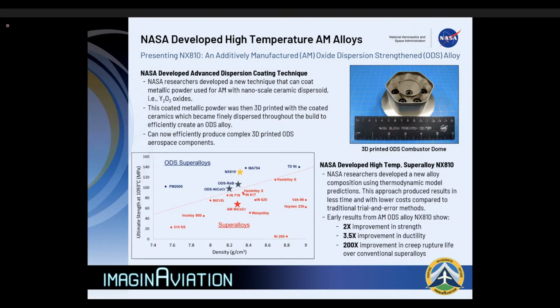And lastly, if we look at its creep rupture life, so basically the life of the component under a static stress at this high temperature, right here on the graph we're seeing a 200x improvement compared to nickel cobalt chrome and other conventional superalloys. But the fact is that those tests were actually still running when we made this graph, and we're now getting to the point where we're seeing 1000x improvement in its creep rupture life compared to nickel cobalt chrome. So you can imagine we're in temperatures and stresses where conventional superalloys would almost instantly break, and we now have components that are lasting thousands of hours.